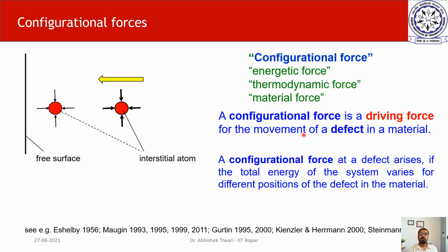So we have used the concept of configurational forces. It is a very old and also very simple concept. If you imagine an interstitial atom which is inside the material and at the surface, there is a change in energy state. At the surface, the surrounding atoms, at least half of them, are not there, unlike when the interstitial atom is inside and from all the sides the bigger atoms are pushing it. So at this point, this atom is happier. So there is a tendency, there is a force, because there is an energy gradient, which is compelling this interstitial atom to go to the surface. Whether or not this atom will go to the surface is a different game, because there might not be a path for the atom to go. There might be a lot of obstacles. Nonetheless, there is a force, and that force is configurational force.